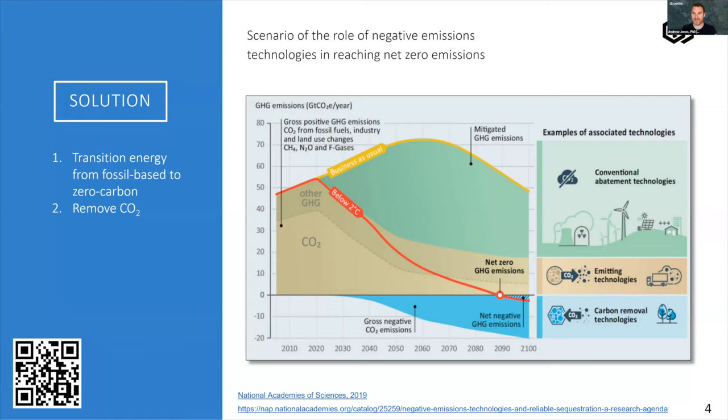With Carba's technology, we're able to torrefy or pyrolyze some of that material and gain up to about 80% of that carbon stored in a torrefied charcoal. And that prevents the decay when we bury it deep in anoxic regions. So the process looks something like this. We take plant and tree waste, which have already breathed in the CO2 and created those carbohydrates and complex polymers. We take that waste material. This is a classic biochar approach for all those familiar, with a bit of a twist on burial.